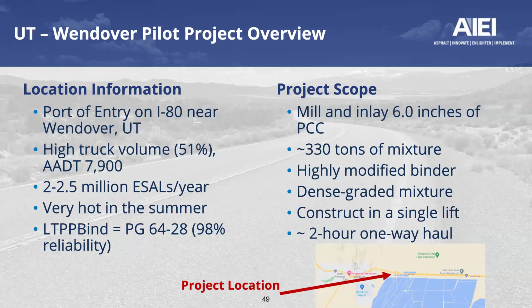This is a very warm location within the state. And if you were to run the typical software at a 98% reliability, you would see that a PG 64-28 would be the recommendation from that software. So in the case of the 76-34, we're stretching the boundary on both the upper and the lower end.